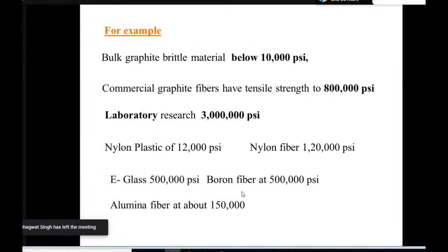That is Griffith's law. The thinner the material, the better the properties it exhibits, because you are removing the flaws from the material. Bulk graphite, a brittle material, has a strength of 10,000 pounds per square inch. Commercial graphite fibers have 800,000. So you can see the improvement in the property between the bulk material and the fiber material.